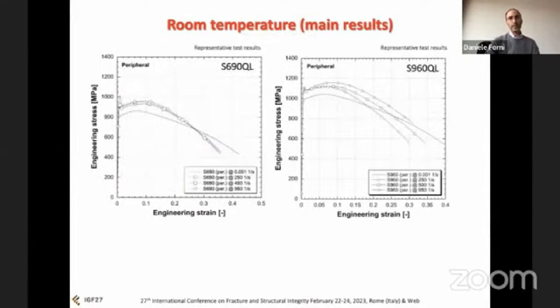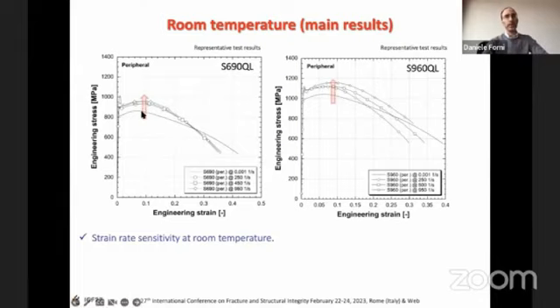So let me say something about the room temperature test very quickly on this stress strain graph, in which, for the sake of simplicity, we have reported only the peripheral zone for the two materials, so S690 and S960. We can see the strain rate sensitivity starting from the quasi-static test to the high strain rate test.